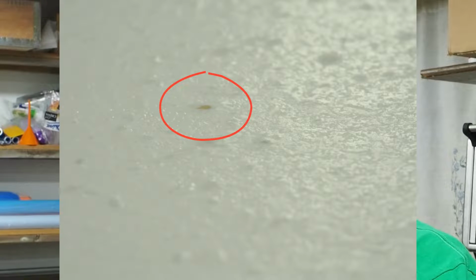Now, this whiteboard has a nice flat surface. It's not porous. And it should give us a much better finish than we had on the previous layup, where I used a piece of cheap furniture door, which was a flat piece of MDF with a thin plastic coating on it, but that coating had a texture. I sanded down that texture to try to make it a little bit smoother. I didn't realize that in the process I had made slight pinholes in that surface. So when I put the wax on it, the wax seeped down in those pinholes, and over time caused that MDF to swell up into little pimples. So I didn't get a very smooth surface on that piece of carbon fiber sample.